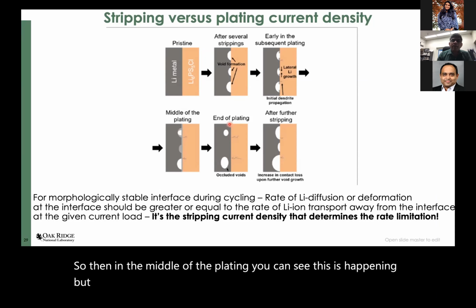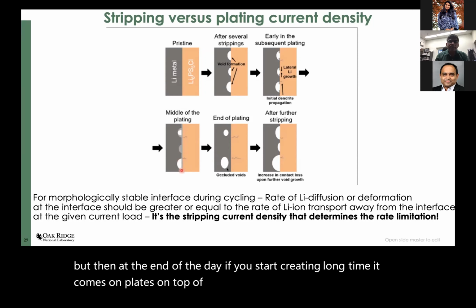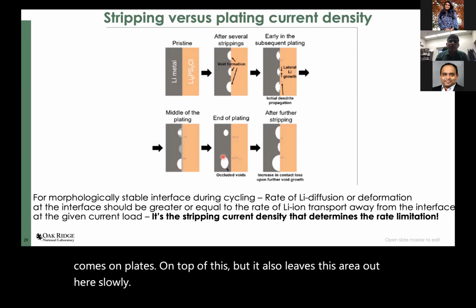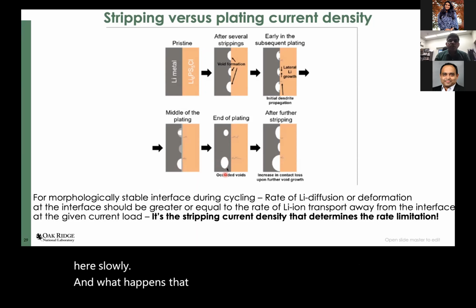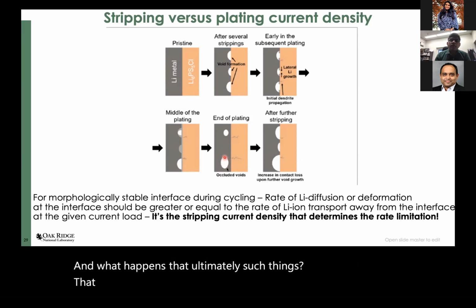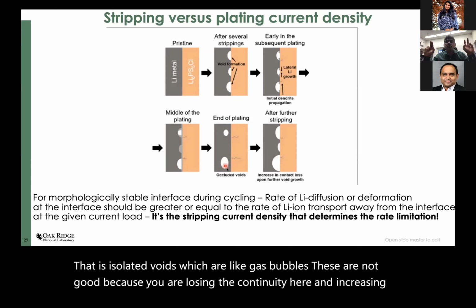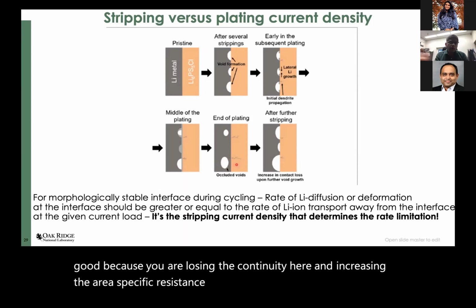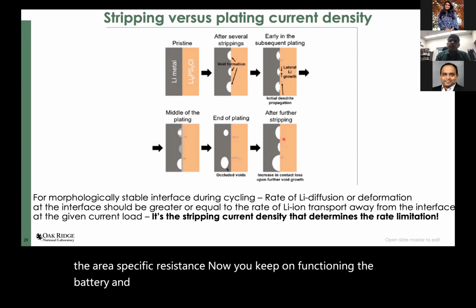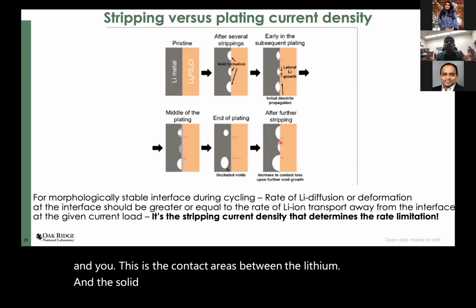But then at the end of the day, if you keep plating for a long time, it comes and plates on top of this, but it also leaves this area out here slowly. And what happens is that ultimately there are isolated voids, which are like gas bubbles. These are not good because you are losing the continuity here and increasing the area specific resistance. Now you keep on functioning the battery and the contact area between the lithium and the solid electrolyte becomes worse. So we have to make sure. So how to solve these issues?